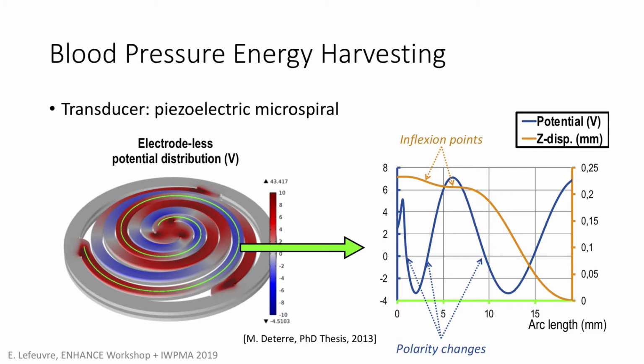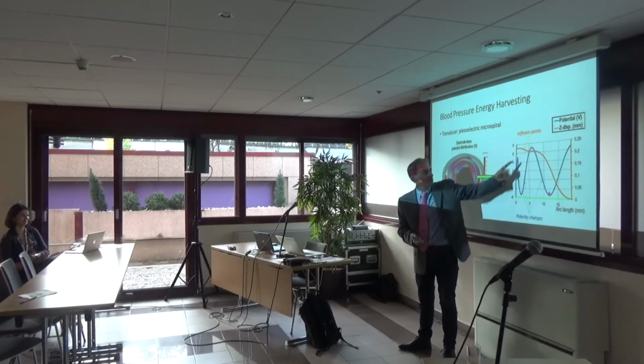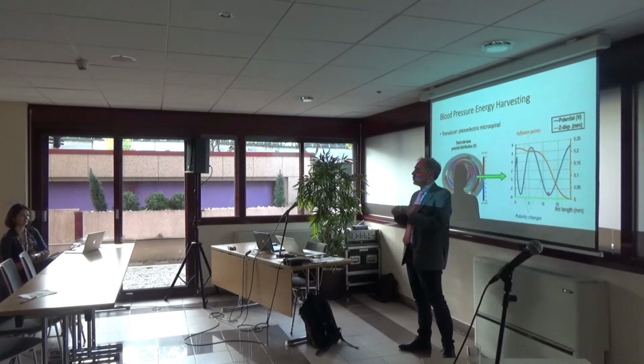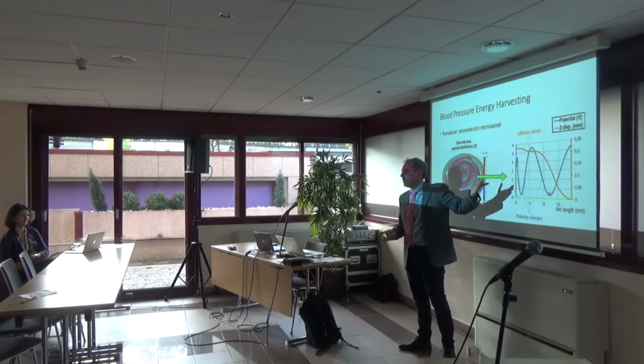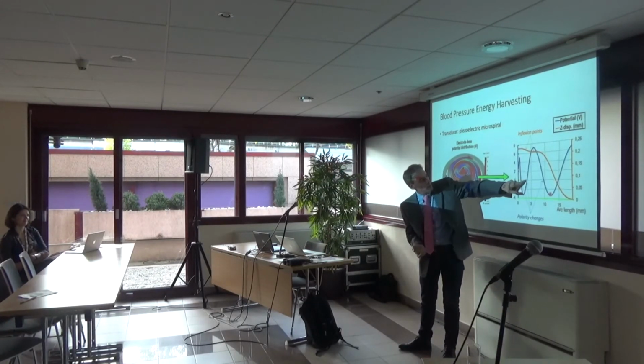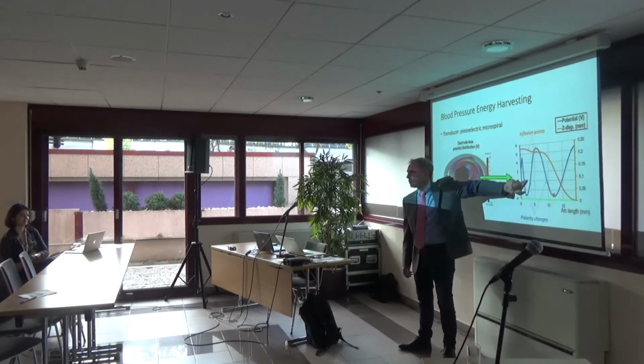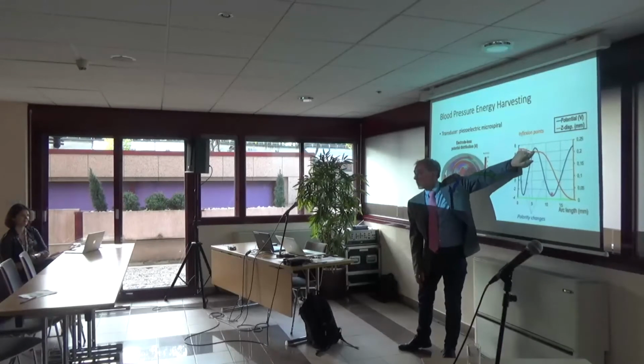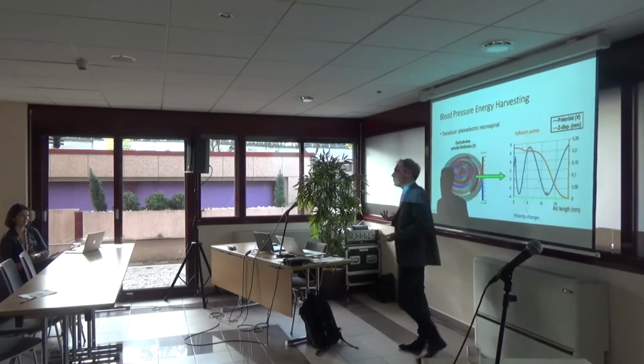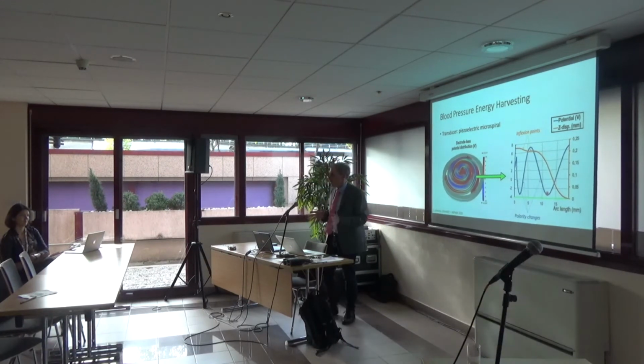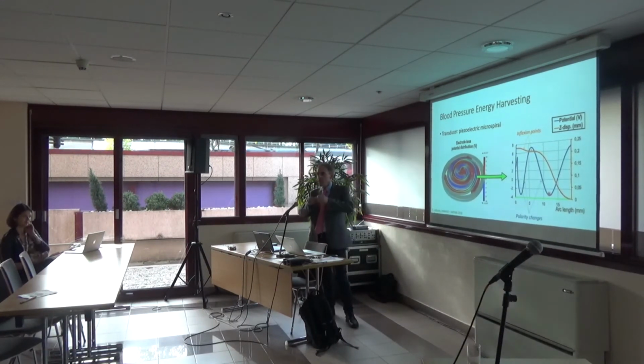And if you look at this, because now you are most of all experts in piezoelectricity, you see that there are inflection points here. The problem is that at the inflection points you have a change of the sign of the stress, right? So you should have a change of the polarity of the voltage. But it's not the case. So here the 0 volt is here, so it does not correspond to the change of polarity. And here it corresponds to a maximum of voltage. So it's not a change of polarity at all. So Euler-Bernoulli doesn't work if we consider that it's equivalent to a beam.